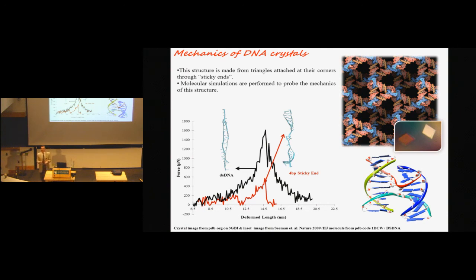They are obtained by self-assembly in a wet situation. Essentially you start with double strands of DNA, and they self-assemble because the ends of these double strands are free. You call them sticky ends, okay? So you actually have base pairs which are not paired with anything at the end of the strand, okay? Then this base pair at the end of this strand is gonna look for a pair that matches from another strand, right? So they diffuse around until they find each other, and then they stick, okay? So after this process completes, you end up with a three-dimensional structure of this sort. It turns out that these structures are fairly brittle.